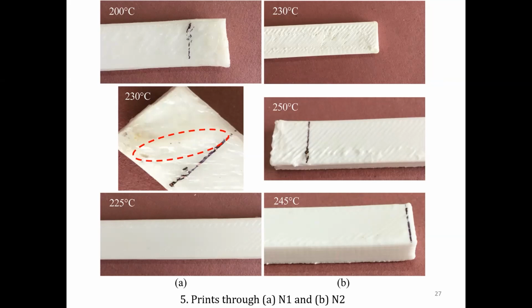So here also, as expected, due to lower HDPE content in H60, small pockets, as you can see in figure 5B, are formed at several locations, which signify that the material did not get deposited. And this is because of the higher viscosity of H60, due to a much lower melt flow index as compared to other compositions. So to counteract, we need to increase the flow of the material.